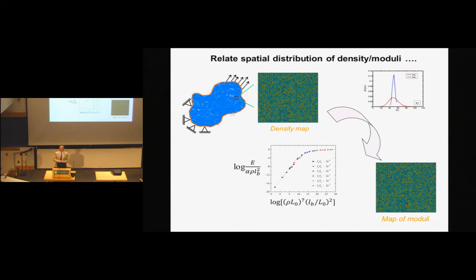So one can think, based on the discussion we had, that you can actually map this to a continuum. How about I use the plot I just described, and knowing the density, I divide the network into small pieces. For example, I divide the network into small little squares, let's say elements, each one of these squares having a certain density of fibers in it. If I know the density and LB for each one of these squares, I can use the curve I showed before to come up with the stiffness for each one of these squares. So in principle, I can map this to something like that, in which now the colors represent elastic moduli. And then maybe I can treat every single square as a finite element and solve a boundary value problem with a continuum model. And then the problem is solved.